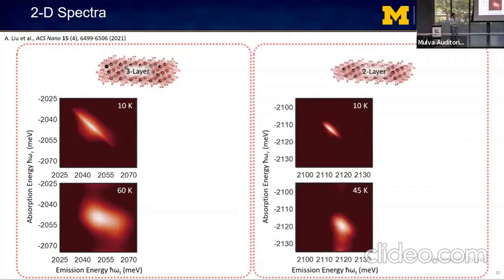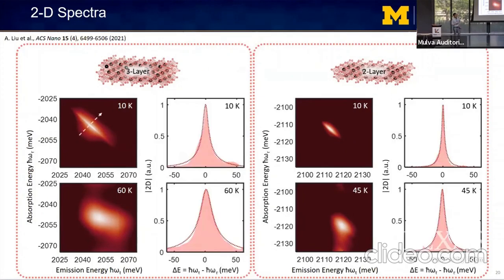And for comparison, here are 2D spectra of the 2-layer nanoplatelets where we observe dramatically reduced homogeneous and inhomogeneous line widths. And to measure the homogeneous line widths, we can take slices along this dashed white arrow. And in these plots on the right, the data is shown as the shaded curves, while corresponding fits are shown as these dotted red lines. And I'll make these statements more quantitative on the next few slides.